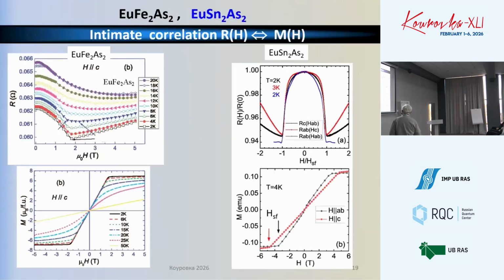And I already showed, but I want to stress that it is tightly correlated with magnetization. The magnetic resistance sharply vanishes when we fully polarize. So in zero magnetic field, there is some additional resistance which is killed by a magnetic field, and then the magnetic resistance transforms to the classical orbital parabolic rise. These are the major features which need to be explained.